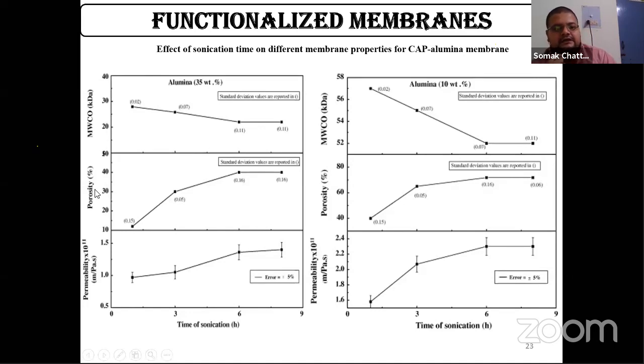Now, there are other factors as well which significantly get increased, the porosity and the permeability. So the porosity gets increased from say 10% to around say 40%, and the permeability, which is a measure of the productivity of the membrane, gets increased to 1 to 1.5. And therefore casting time or the sonication time has a profound effect on the functionalization of the membrane.